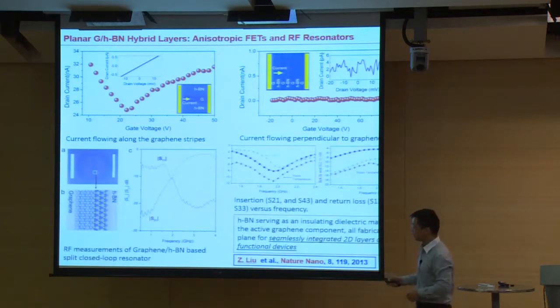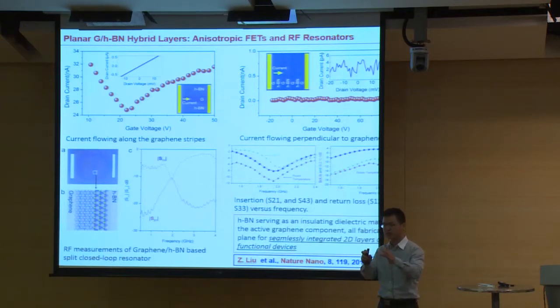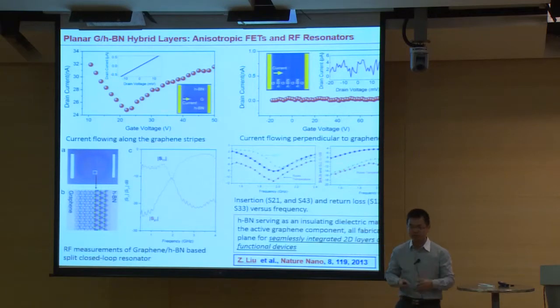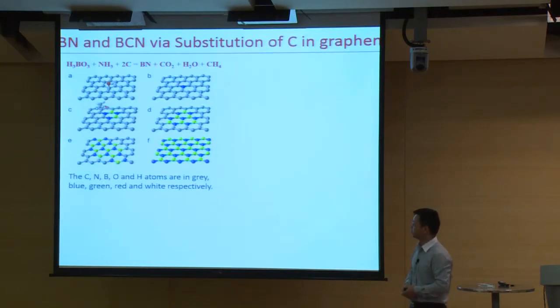And we also demonstrate that if we make some graphene lines filled by boron nitride, we can get graphene-boron nitride planar radio frequency resonators, and the response frequency is around 2 GHz. So this work tells us that we are able to do shape engineering of graphene-boron nitride planar structures. So we can design whatever we want, which areas are boron nitride, which areas are graphene, to meet our needs. And if we can incorporate TMD material in this system, I think the system might be much more interesting and fantastic.